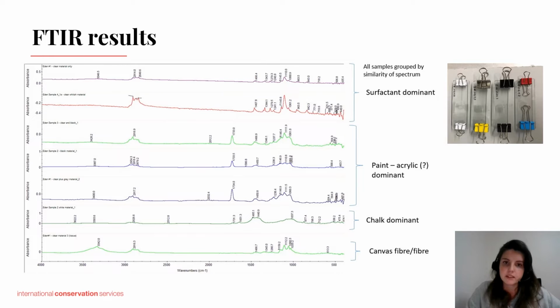The exact process behind the migration of surfactants is relatively unknown. However, the concentration of surfactant in the makeup of the paint, thickness of the layers and primer type of the painting, and ongoing environmental conditions all play a part. With hundreds of layers of paint differing in thickness, this artwork could be said to be quite susceptible.